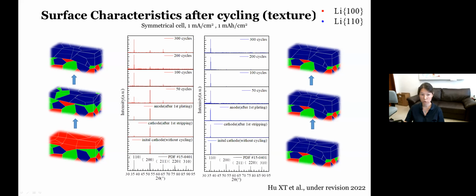So that is to say, the surface is losing its original texturing of the 100, and eventually it moves into 110. Now, in comparison, if you look at the lithium 110, this diffraction is stable towards the end. That is to say, along with cycles, the texturing is not changing at all.